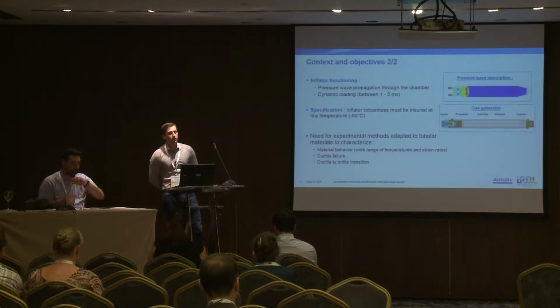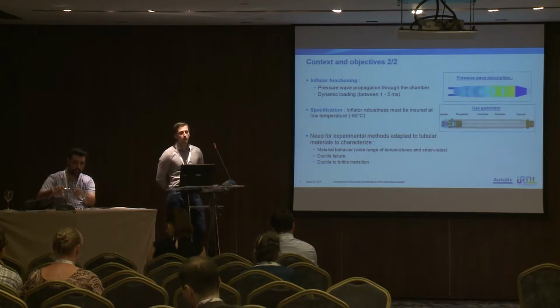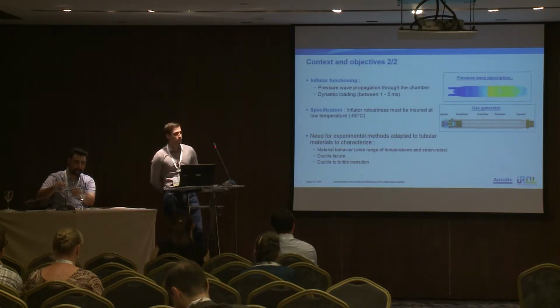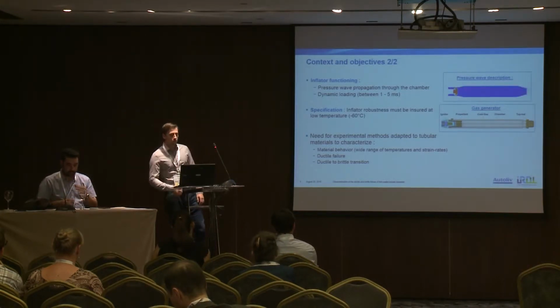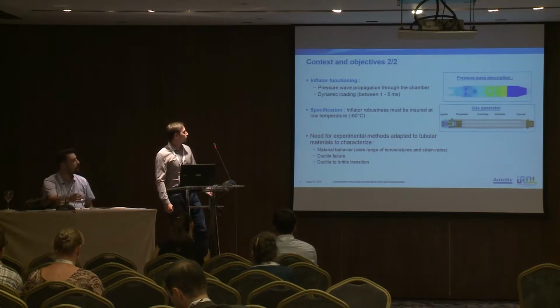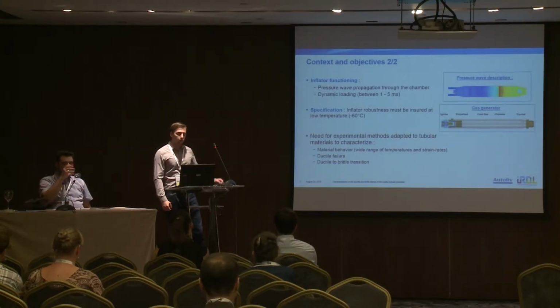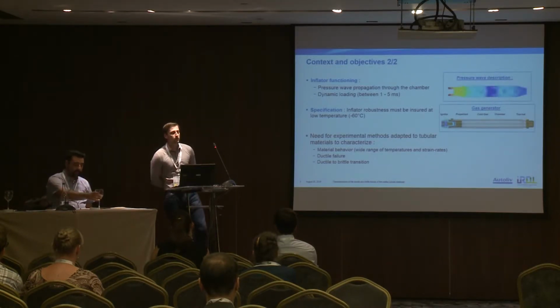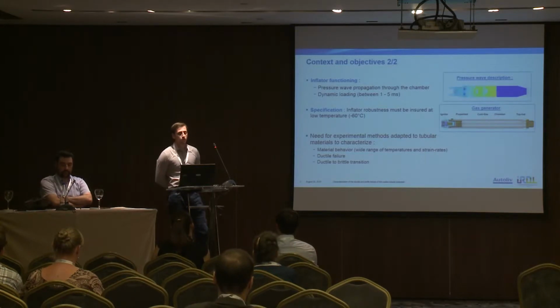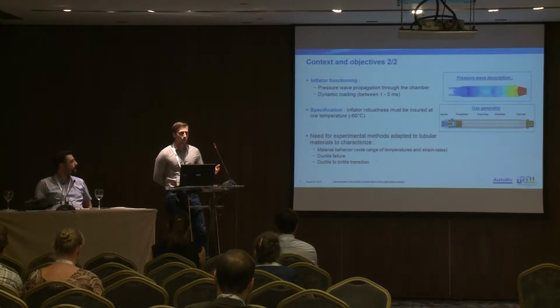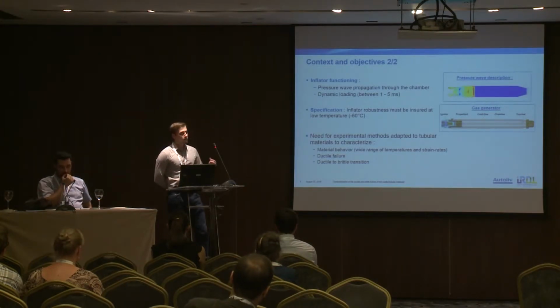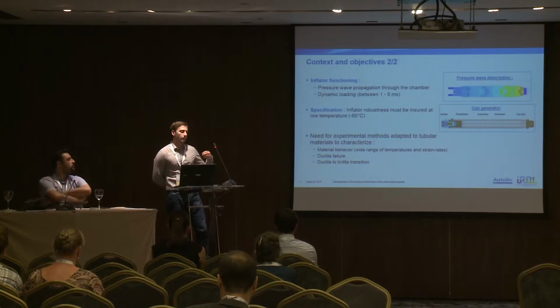Also, during inflator functioning, there is a dynamic loading of the chamber due to a pressure wave propagation through the chamber. And if that's not sufficient, you are in the automotive industry, consequently you have to validate some specifications, and the most critical specification is that inflator robustness must be ensured at low temperature, minus 60 degrees Celsius. So here you combine high-strength steel with a very thin microstructure, high strain rate loadings, and low temperature conditions. So brittle failure can occur, and this mode of failure is really critical. So we have to be sure that it does not occur.